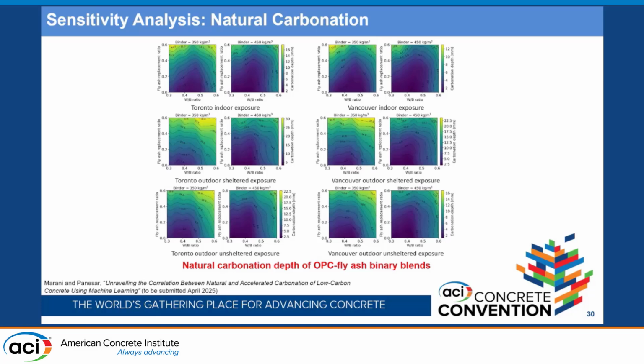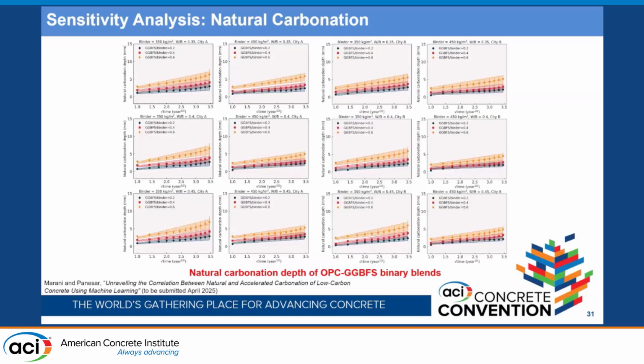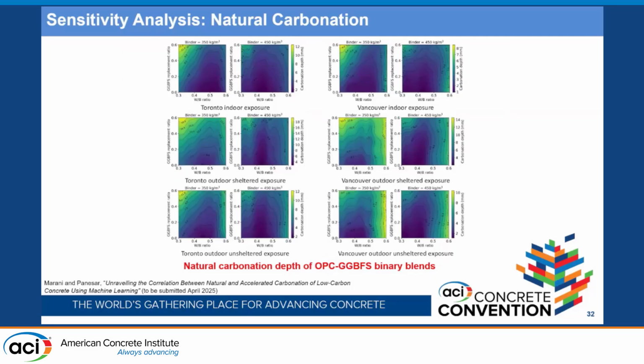So for the natural carbonation, we actually explore different scenarios. We took the environmental parameters or the climatic condition parameters of two cities, Toronto and Vancouver, and we consider different types of exposure: indoor exposure, outdoor sheltered, and outdoor unsheltered. And again, this is the interplay between different mix design parameters and the environmental parameters. When we compare the results with the findings in the experimental work in the literature, we can see that the model did a very good job in differentiating between, for example, outdoor or indoor exposure types. And we have the same type of results for the slag also.